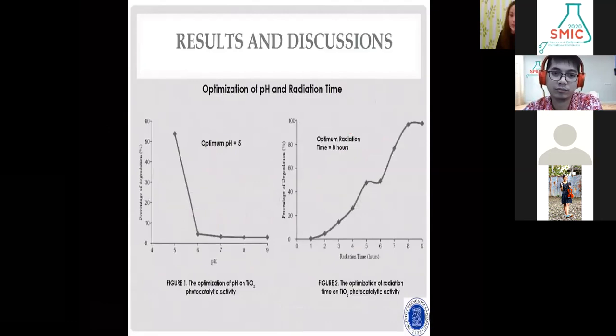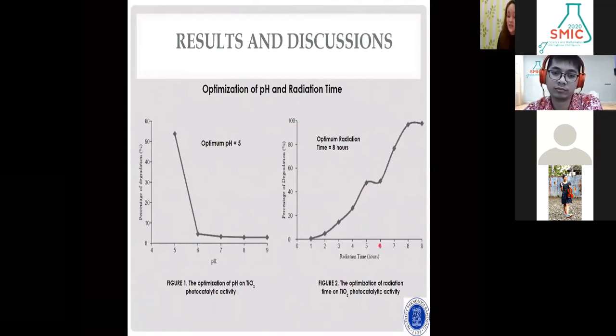And then here we are going to the optimization of pH and radiation times. Figure 1 shows the optimization of pH of titanium dioxide photocatalytic activity. And figure 2, the optimization of radiation time on titanium dioxide photocatalytic activity. You may see here that the pH of the analyte solution, which is the methyl orange solution, can determine the rate of photocatalytic activity of titanium dioxide. At pH 5, the highest percentage of degradation was found, as a slightly acidic atmosphere will increase the number of OH radical intermediates because the reaction rate of photocatalytic activity is greater. The result is that the optimum pH is 5 in this research.